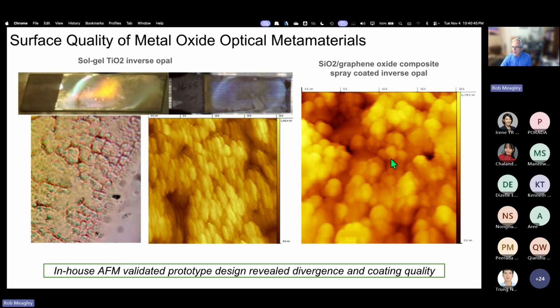On the right, we have a graphene oxide silicon dioxide composite that was spray-coated to make a similar inverse opal. These are hollow spheres of about 90% graphene oxide with a little bit of silicon dioxide binder. The topology of the titania surface is about 1.33 microns, and we're reading half micron sized spheres with approximately 20 nanometer resolution. You can see easily the surface roughness of those spheres. In the case of the graphene oxide, we've got about 4 microns from the deepest pit to the tallest peak, and we're able to see some of the surface topology in this image for those spheres.